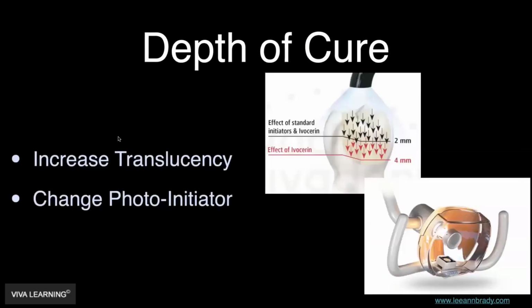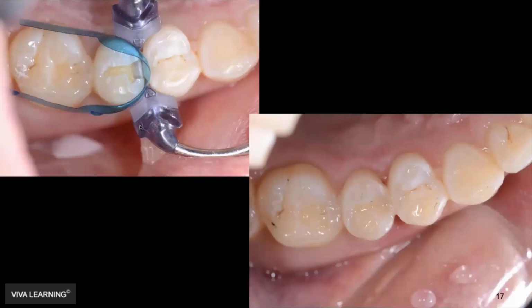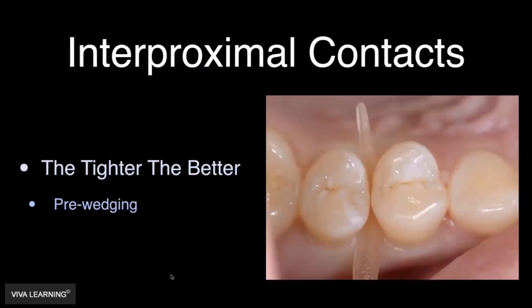Okay. So between managing the direction of the polymerization shrinkage so that we reduce stress on the bonded interface, increasing the translucency, and changing out photo initiators, we actually came up with bulk fill composites where some of them have better physical properties than some of the non-bulk fill composites. And again, you get to choose the kind that can be standalone restorative materials versus the kind that need to have a cap layer on top of them.